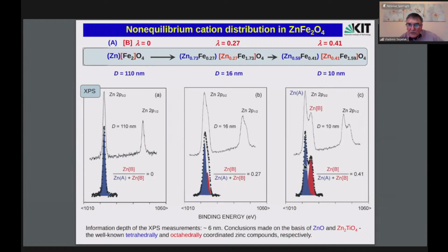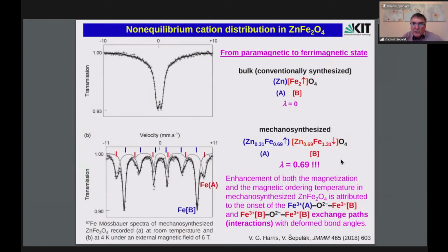From the intensity of these spectral lines, we can calculate the so-called degree of inversion of the spinel structure. In this case it is 0.41, the concentration of zinc occupying octahedral sites in the spinel structure. That means it is very nice information that we have a non-equilibrium distribution of zinc cations. To complement this information, we have to look at iron, and in this case Mössbauer spectroscopy is very powerful. You see here we also have two subspectra, two sextets, corresponding to iron cations on tetrahedral sites, the blue lines, and octahedral sites, the red subspectrum.